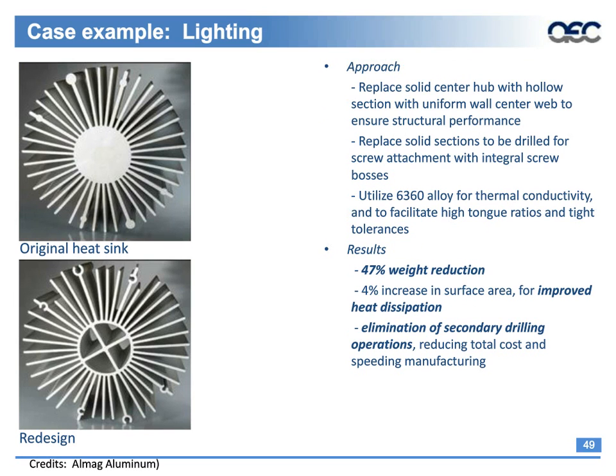After discussions with the extruder, it became evident the heatsink didn't need to have all that mass as much as it needed to have greater area for heat dissipation. For this application, with cooling the LEDs, they had to have area that pulled the heat away as opposed to a big solid blob of aluminum in there. So the existing heavy profile was redesigned. It incorporated four hollow profiles there. And towards the end of the profile, we have these little screw ports that were incorporated.